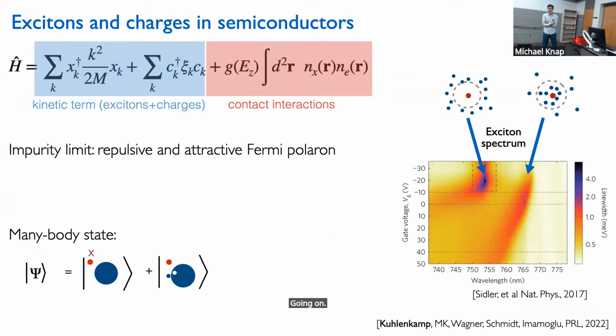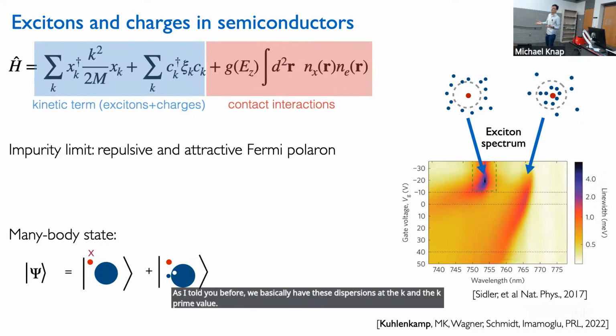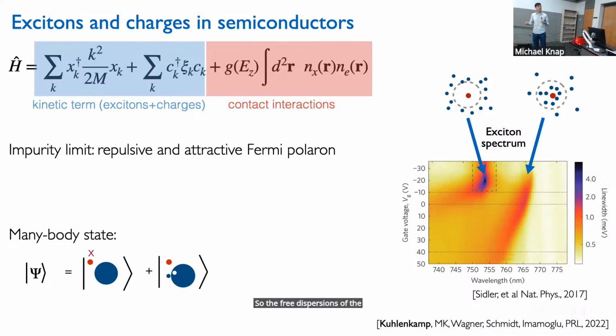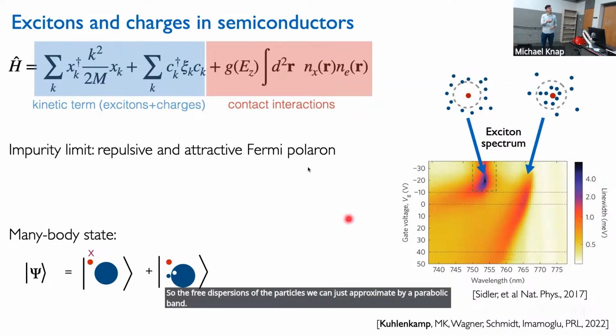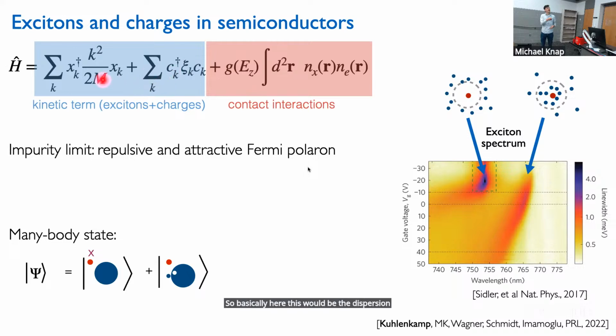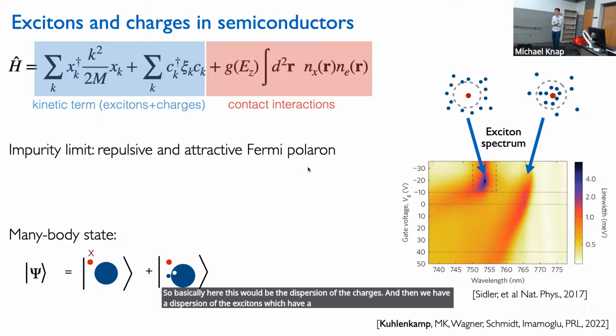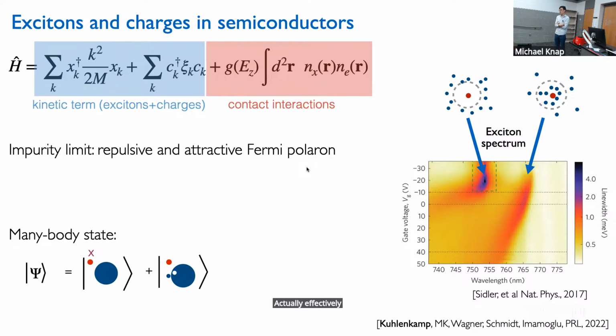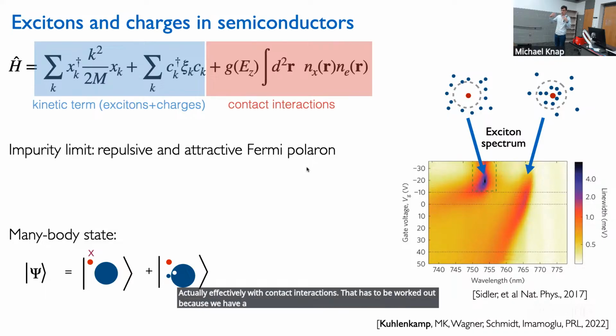So when we want to model what is happening in the system, as I told you before, we basically have these dispersions at the K and the K prime valley. So the free dispersions of the particles we can just approximate by a parabolic band. So basically here, this would be the dispersion of the charges. And then we have a dispersion of the excitons, which have a different mass, of course, because this is a two-particle bound state. And then they interact with each other, actually effectively with contact interactions. That has to be worked out because we have a charged object and we have to do a multipolar expansion.